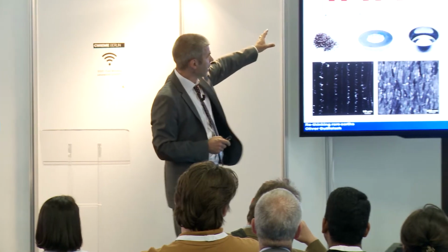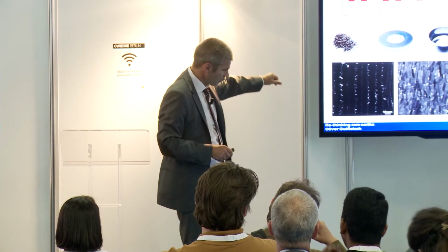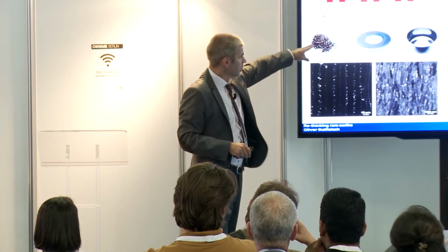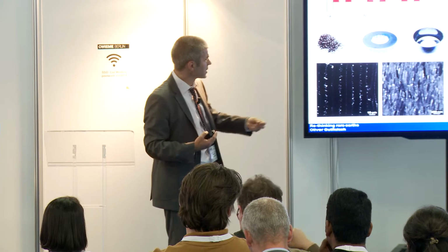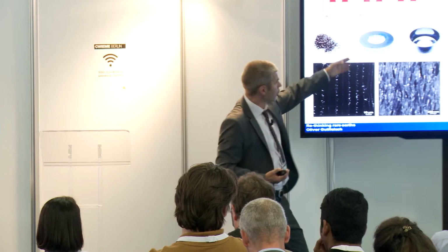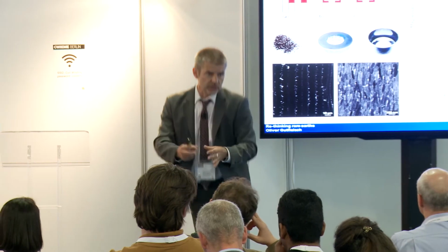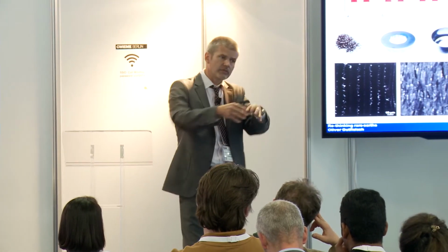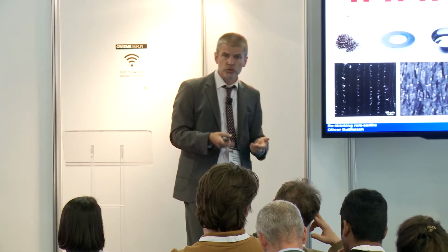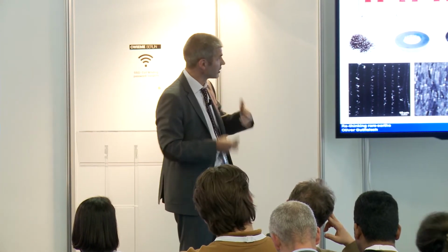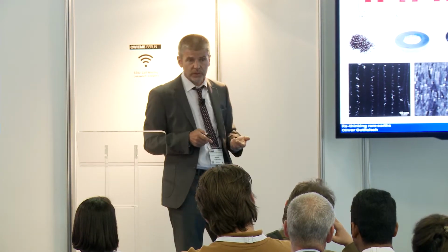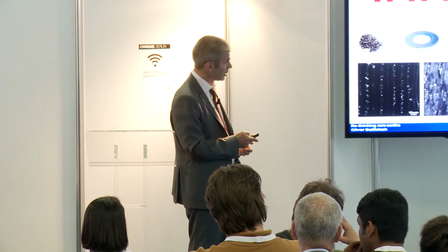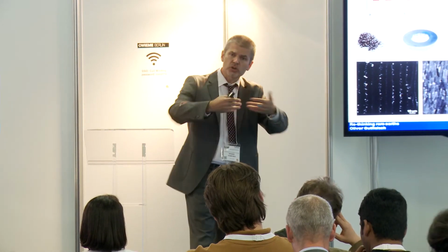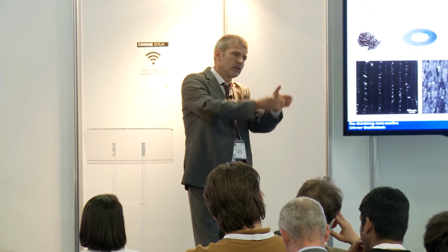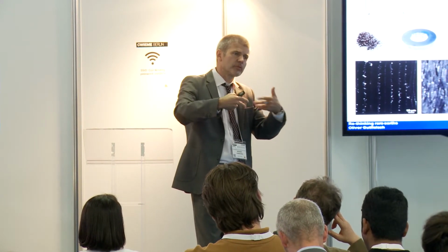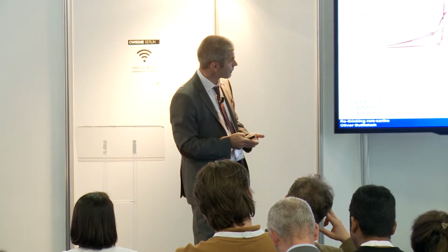Another way is to make net-shaped magnets by hot deformation. We do this in Darmstadt and Fraunhofer. We have rapidly quenched materials, we can make them into a hot press magnet, and then we can extrude these ring magnets. Then we have quite complex shapes with very little waste produced. You can see on the right-hand side also very high magnetic properties comparable to the sintered conventional powder metallurgy. The problem here is that at this stage it is a discontinuous process. We make them step by step, and that of course makes it economically problematic.